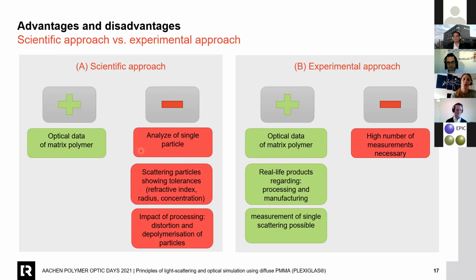The disadvantage of this scientific approach is the analysis of the single particle. The particle is only one part of the whole process, so here we pay no attention to the other parts of production. And we use industrial particles, so they can show tolerances in the refractive index, the radius, or the concentration. Another disadvantage is that we can have distortion or depolymerization of the particles during the process, and it's nearly impossible to handle these effects in the calculation.